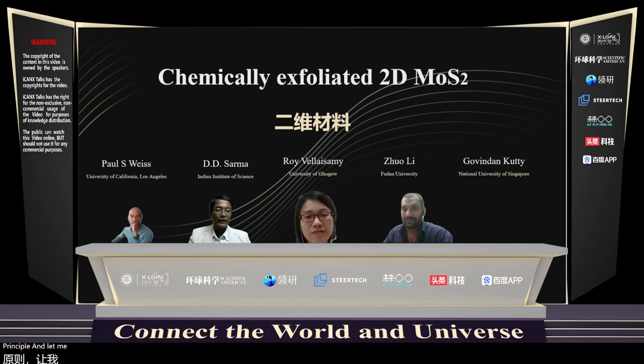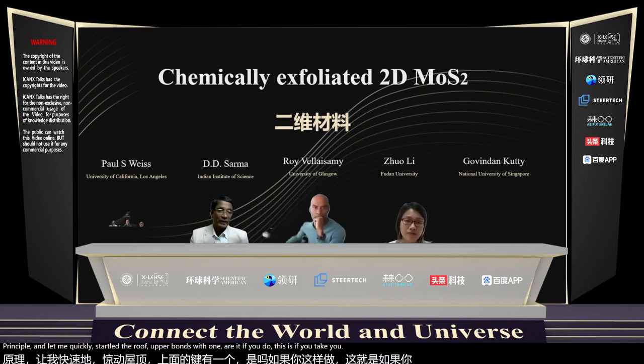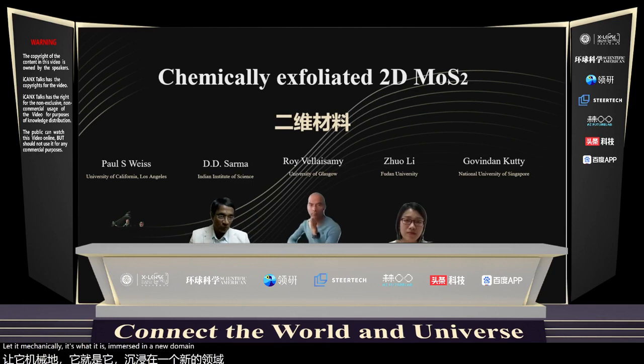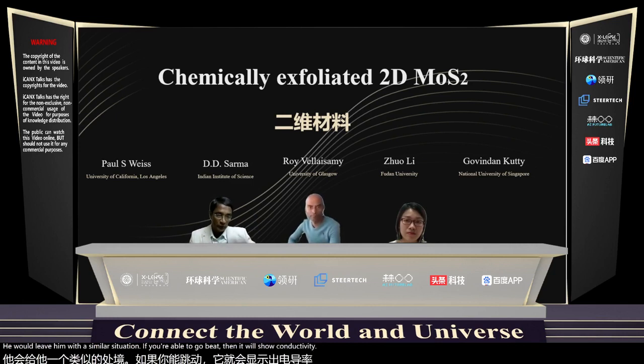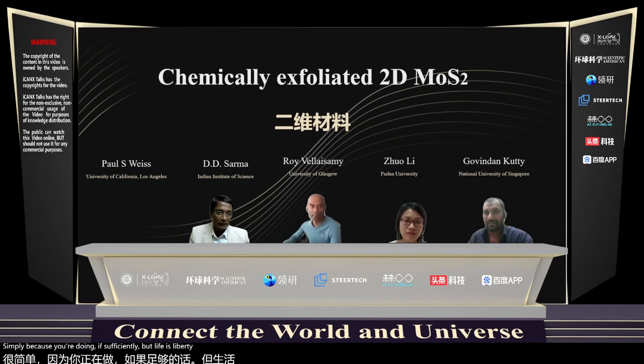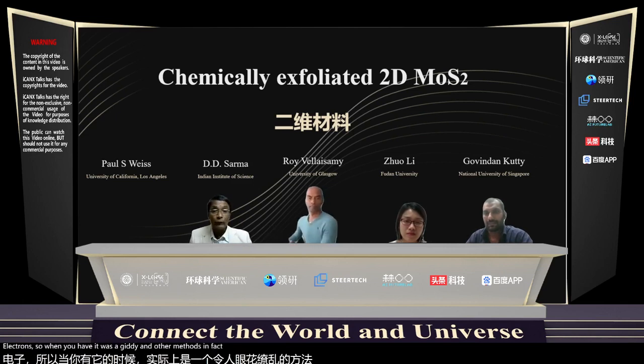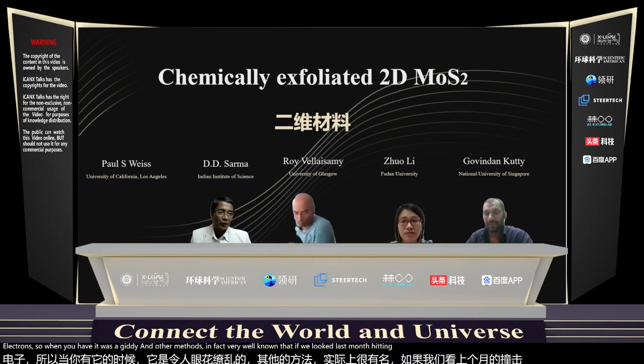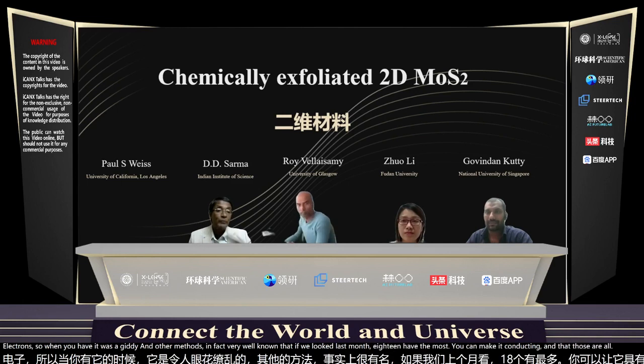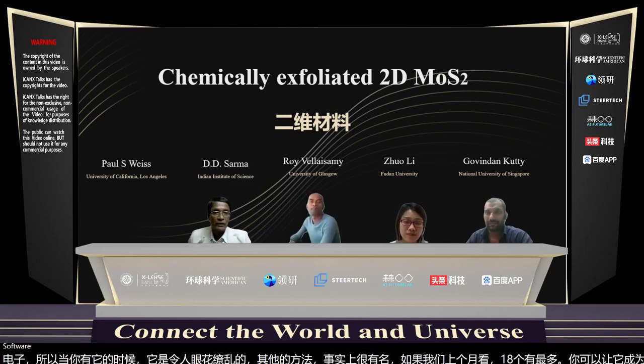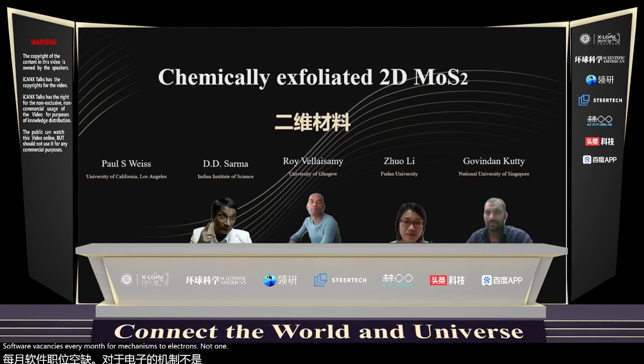First of all, let me quickly touch on several subtle points. If you take your mechanically exfoliated MoS2 and dope it with lithium, potassium, etc., if you're able to dope it sufficiently, then it will show conductivity. But life is never ideal. MoS2 always has defects, sulfur vacancies. The sulfur vacancies also dope electrons. In MOCVD and other methods, it is very well known that if you do a plasma etching of MoS2, you can make it conducting. Those are all coming because of sulfur vacancy. I suspect every sulfur vacancy dopes 2 electrons, not 1. So it's a very strong doping.